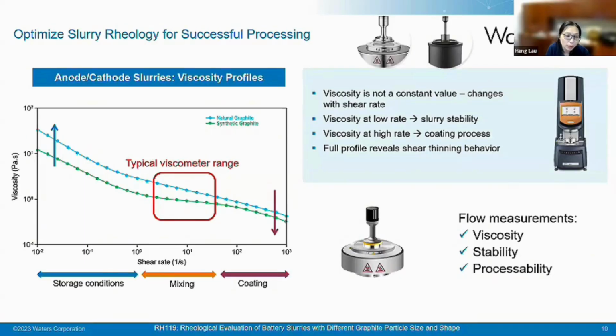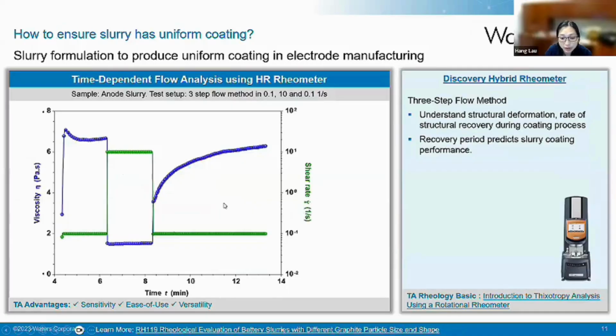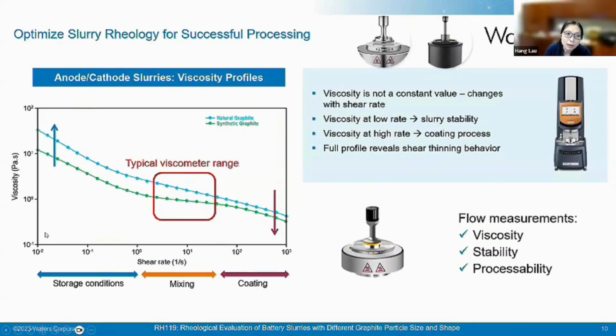And rheology will be helping you to understand the consistency of the material and how it shears. As I mentioned, rheology, slurry is known to have a shear thinning property. So oftentimes when you're low shearing, it will be mimicking the slurry stability. Once you have increasing shearing, you will actually see a reduction of the viscosity. So that's a very important piece of information you can get.